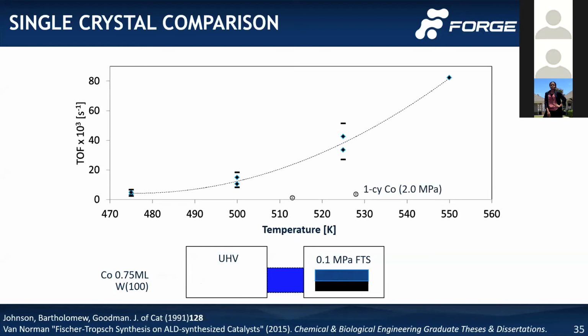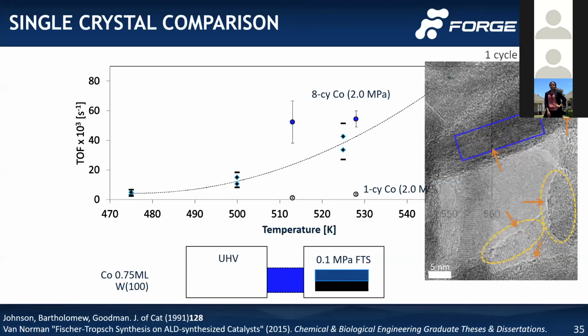When we plot our cobalt ALD catalyst on here, the 1 cycle has very low turnover frequency, as expected for very small nanoparticles. The 8 cycle cobalt is up here within the error bars for that turnover frequency study. So it appears the cobalt was depositing more in a single crystal form. What we saw on the surfaces is that you actually have very small nanoparticles, but also these crystalline surfaces. So it's likely that some of the cobalt was depositing as a single crystal on that support.